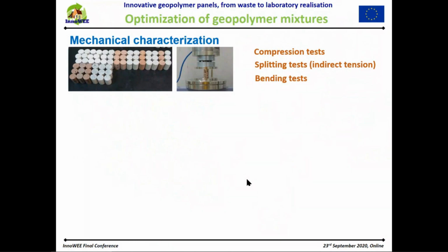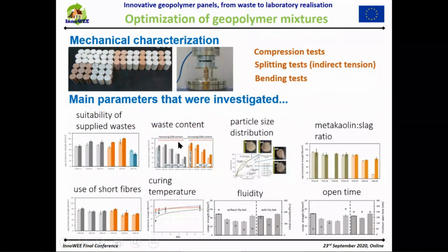About characterization, the first characterization serving to qualify is certainly mechanical characterization performed on all samples produced: compression test, splitting that evaluates the tensile stress, and bending stress. Then other parameters were investigated. These are some examples. For example, the suitability of a waste, the content of a waste used, bricks or cement, the particle size distribution. Then talking about the reaction, the rate of the reagents, the use or not of short fibers, or what kind of short fibers. Then the process: curing temperature, fluidity, open time, and so on.